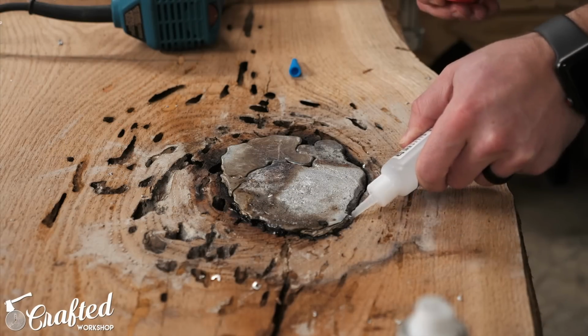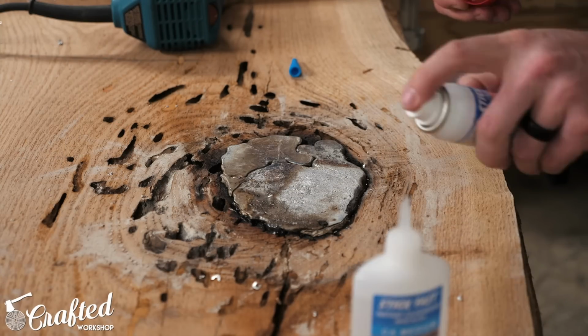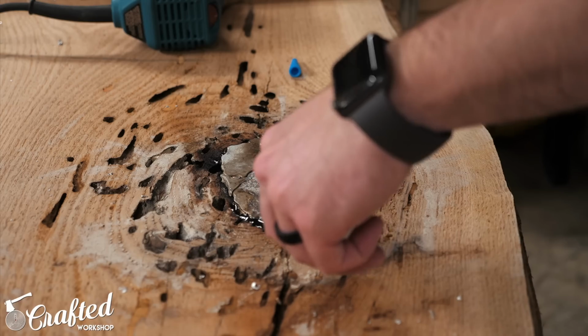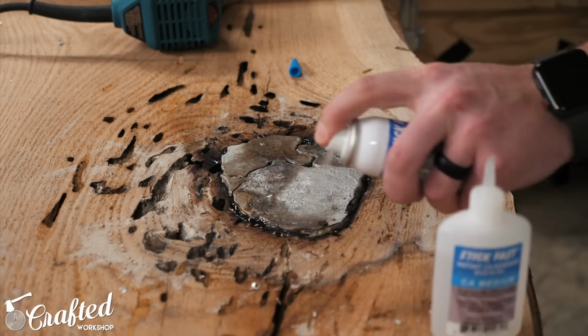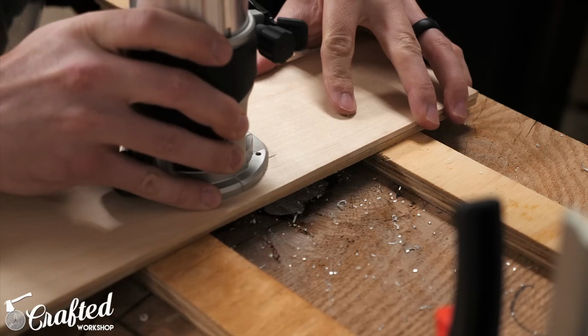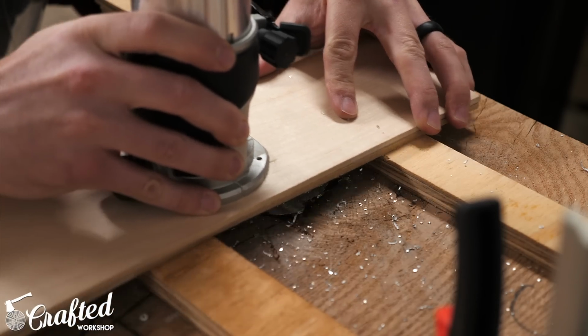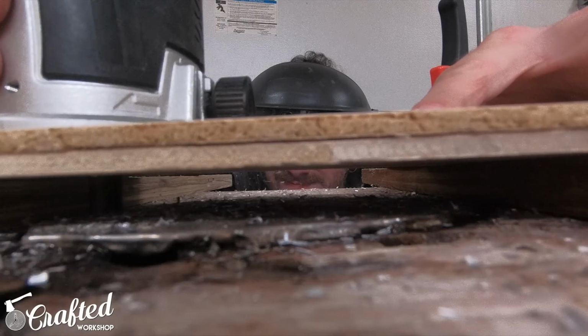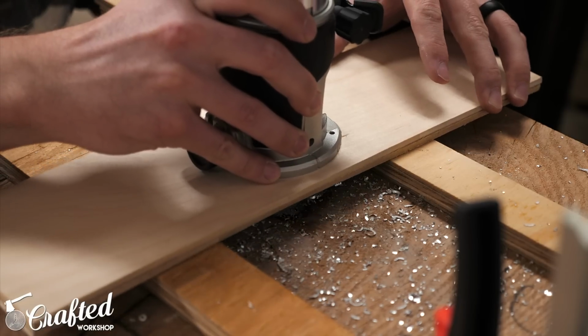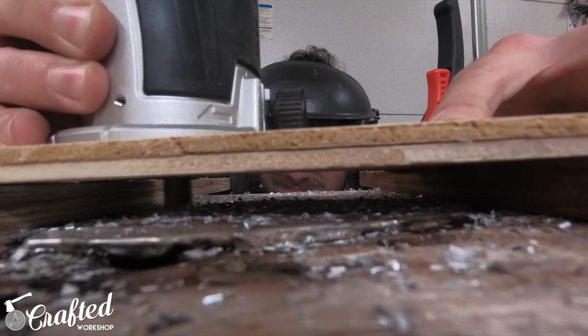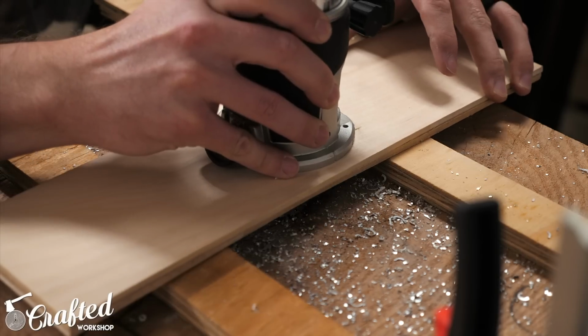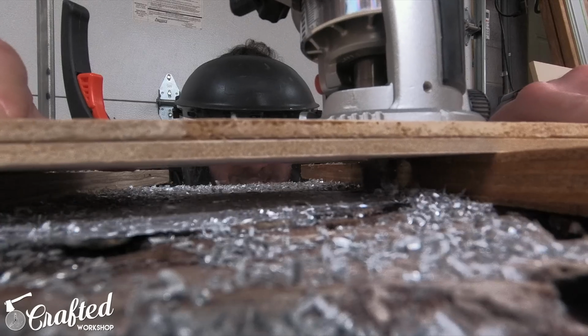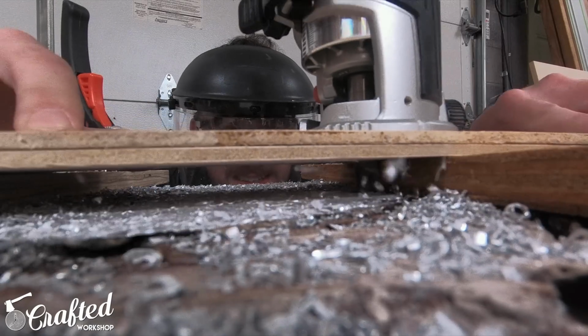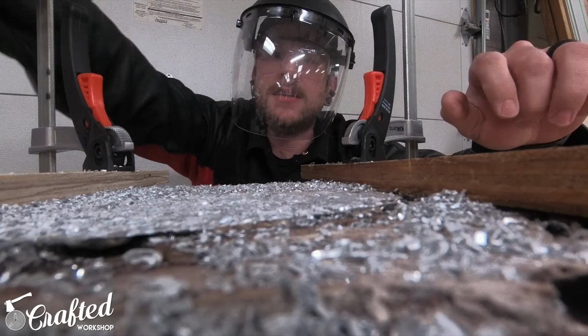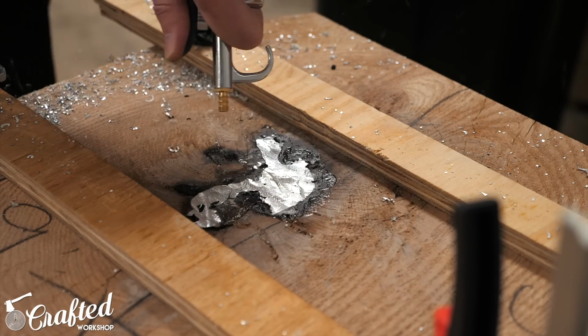While flattening, I also realized that the aluminum pieces were still a little loose in the slab just from the wood burning out, so I stabilized them with some CA glue, and this really helped with the routing process. I was getting some vibration and the bit was catching a good bit, and stabilizing the piece of aluminum totally solved this problem. I just continued flattening until I had both pieces roughly flush with the surface of the slab, and this was a really slow process. The aluminum heated up way too much if I tried to make deeper passes, so it was best to just take my time here.